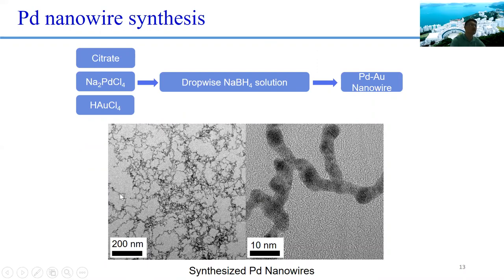Okay, so we synthesize the palladium nanowires. Okay, so simply just using sodium borohydride to reduce the palladium precursor, and you get palladium nanowires. And we further make the alloy with gold, okay? Because gold actually has a larger atomic radius than palladium. So when you alloy with the palladium, then basically the lattice constant of palladium will become larger. So it gives you additional tensile strain, okay? So you can use the method that can also make the palladium gold nanowires.